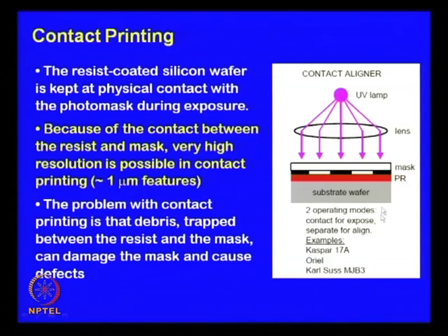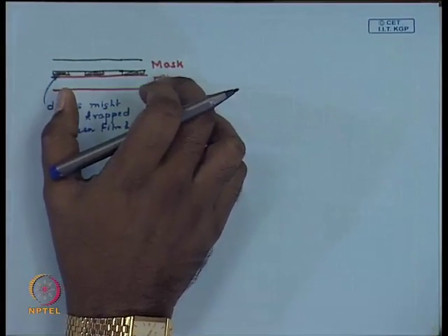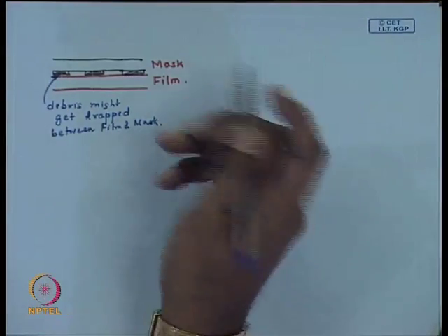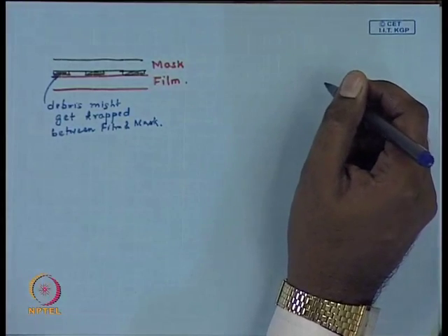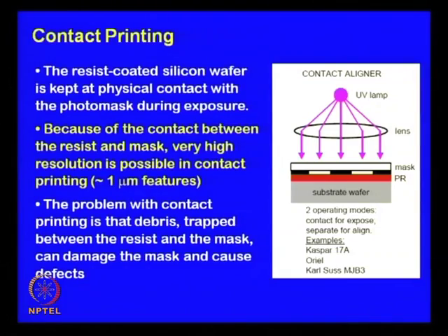the operation is very simple. So, one is the contact, which is for exposure, and then separate for align. So, you place the mask on the film, you expose, then after exposure is over you physically detach the mask from the film, and the film is taken for subsequent processing. Mask with minimal amount of cleaning maybe is reprocessed.